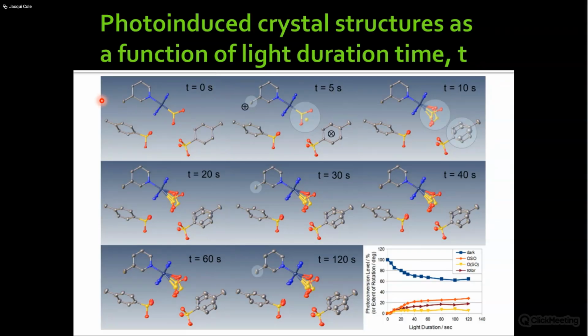So it's all on the same crystal, but basically I collect the crystal, for example, in the dark state at time equals 0, right? So you've already seen that on the previous slide. That's your asymmetric unit. And then I do a series of repeat experiments where I apply the light first for 5 seconds, and after 5 seconds I switch off the light. I keep everything cold. The same crystal stays on the diffractometer all the time, and then I collect a full crystal structure, right, with just 5 seconds of light on it, having switched it off.